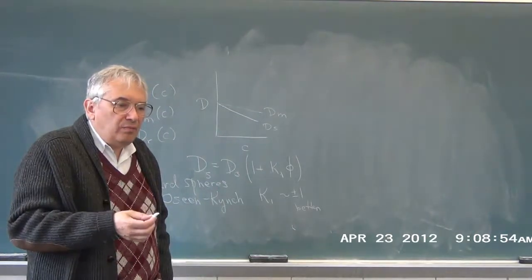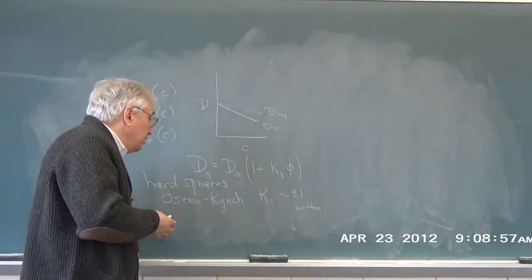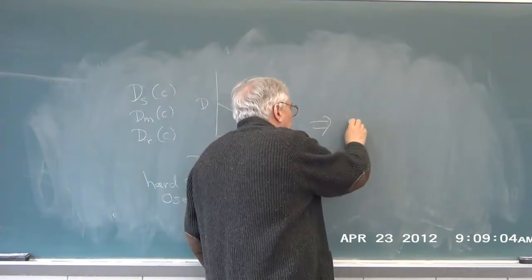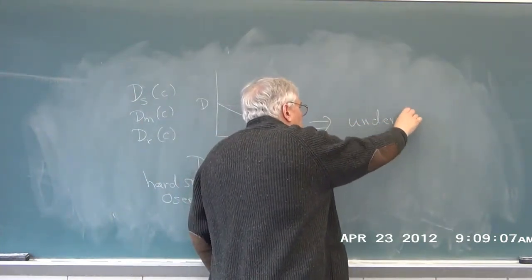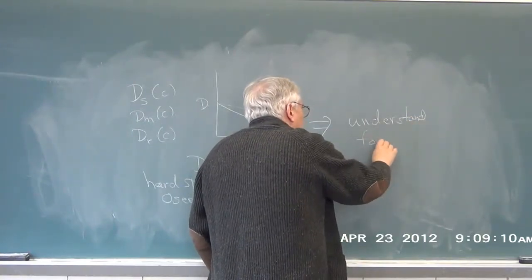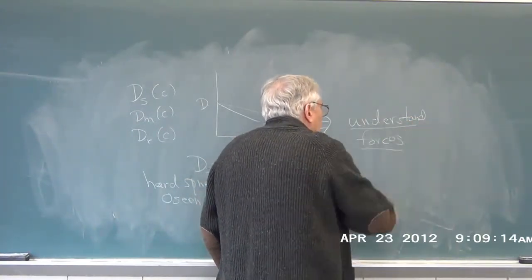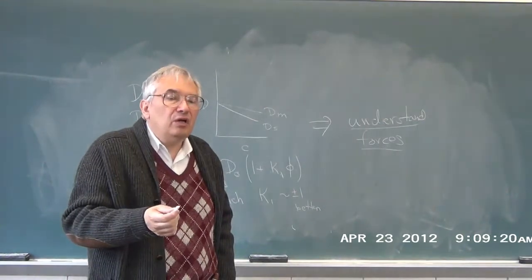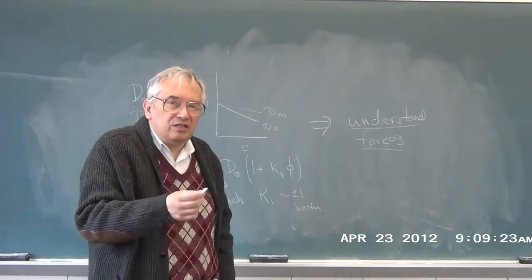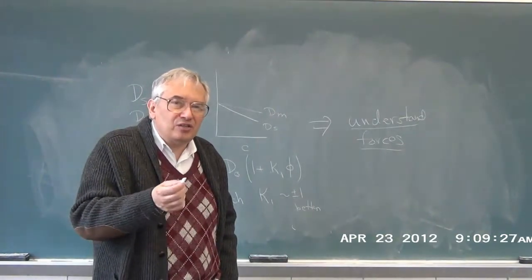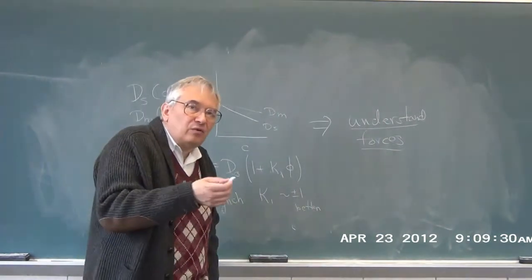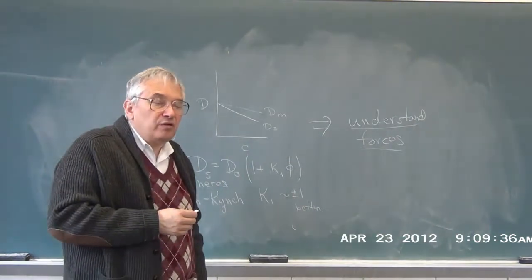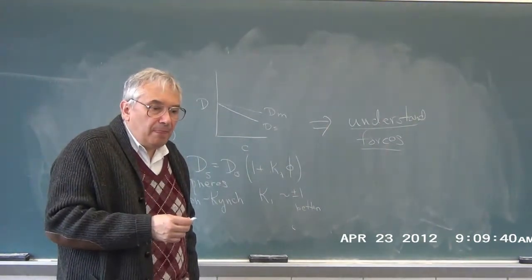The statement that we are seeing and able to calculate the slope reasonably accurately says, there's an implication here, and the implication is that we understand the forces. There has been a very long time, going back, say, to the Kirkwood-Riseman model, where people say, we will treat the hydrodynamics with the Oseen tensor. We will treat volume exclusion by saying these things are hard spheres. However, the question is, is this right, or are we completely off the track, given that we're on a very atomic scale? And the answer, based on these calculations, it appears we are very much on the right track in what we did. Okay?